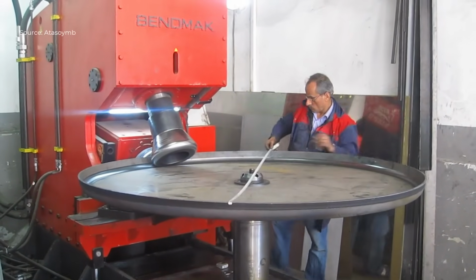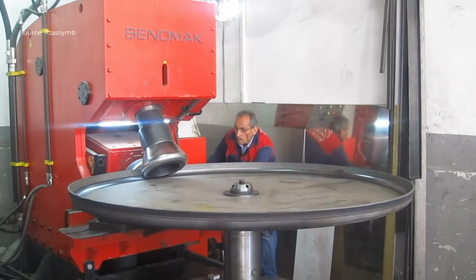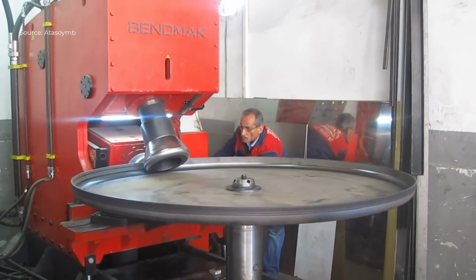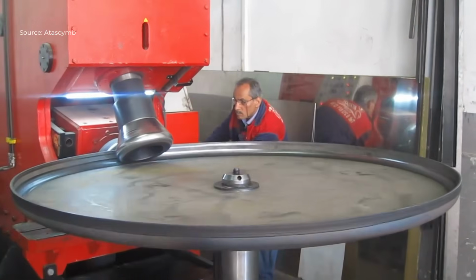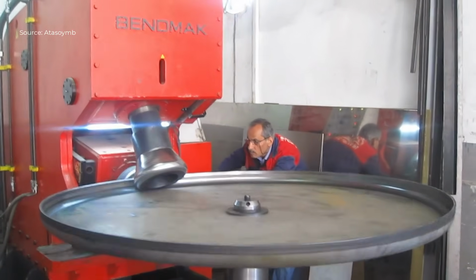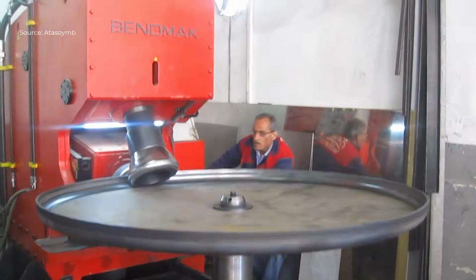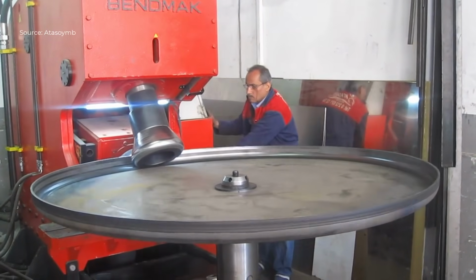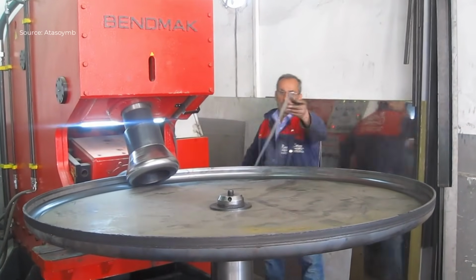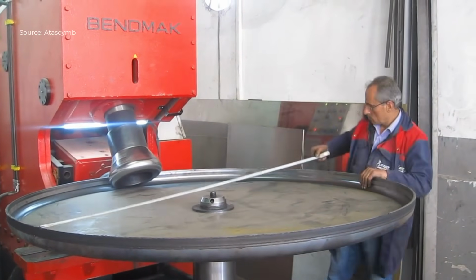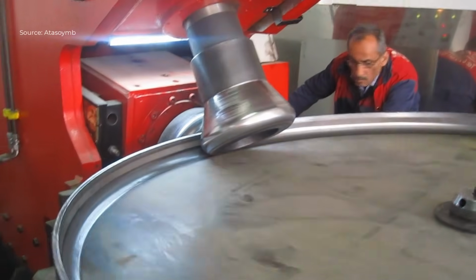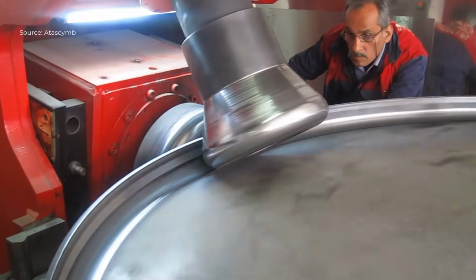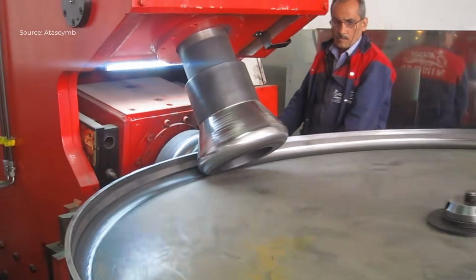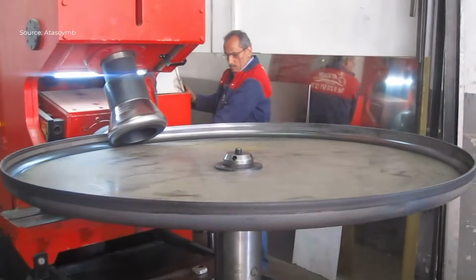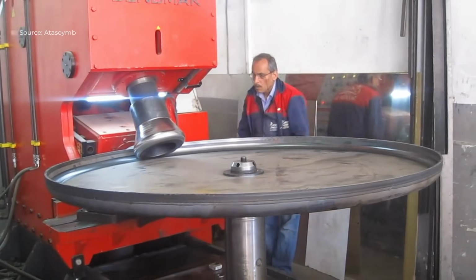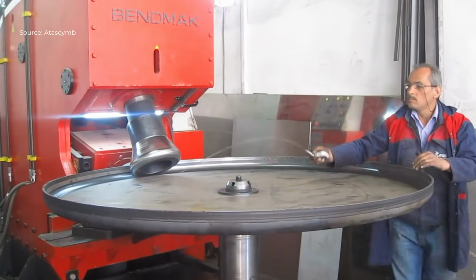The machine's rigid frame and hydraulic control system ensure stable force distribution, which is essential when forming plates up to 16 millimeters thick. Operators carefully monitor alignment and pressure throughout the operation to achieve uniform thickness and accurate geometry. This forming method improves material strength by maintaining continuous grain structure and reducing internal stresses. As a result, the finished flanged or dished steel component meets demanding industrial requirements for pressure vessels, tanks, and heavy structural applications.